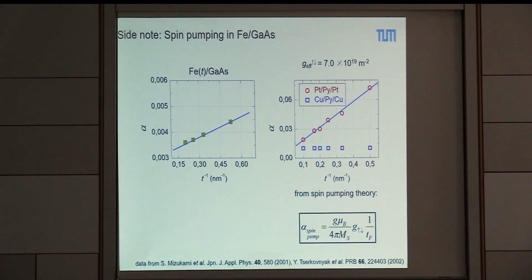But if you sandwich between platinum, you can see an increase of spin pumping, which is like 1 over the thickness. Now, you can extract from these measurements a contribution to the Gilbert-like damping, which is the spin pumping contribution, which contains the g factor, the magnetization, the 1 over the thickness, and also this spin mixing conductance. And it's typically somewhere around 10 to 19 or so.